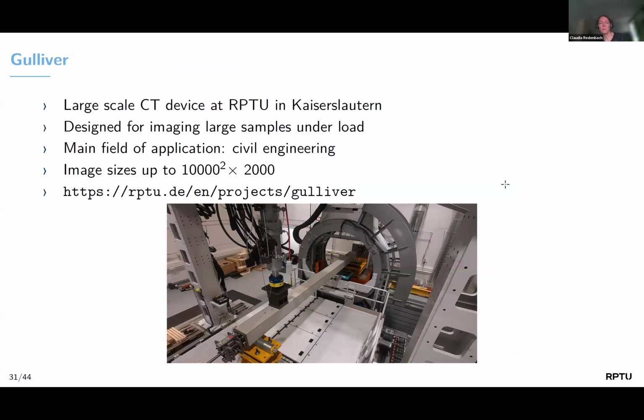Why do we do that? Well, recently we established a large computed tomography device at RPTU in Kaiserslautern, which is called Gulliver. And it's designed for scanning large samples under load. So here you see an example. We can scan concrete beams up to 6 meters length and subsequently apply some load and scan these beams under load, and this way visualize the evolution of crack systems, for instance, in the concrete.